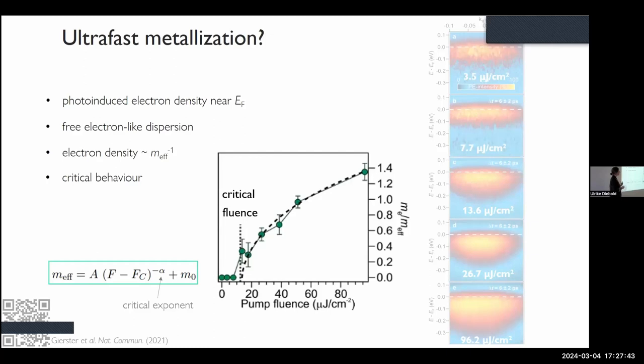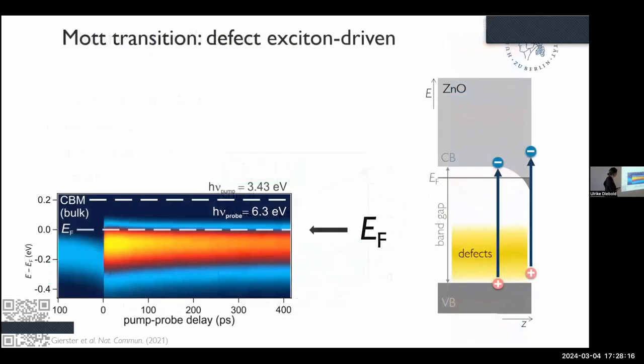the fast recovery time. You remember it recovers on picosecond timescales. Very often these phase transitions are leading to a hot metallic state that lives for nano, micro, milliseconds. And due to the low excitation density and due to the fact that hot zinc oxide is still a semiconductor, this is possible. Yeah, and this is quite a nice result if you're into these photo-induced phase transitions.